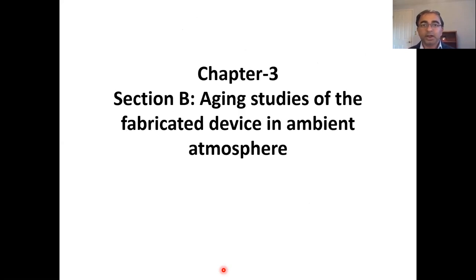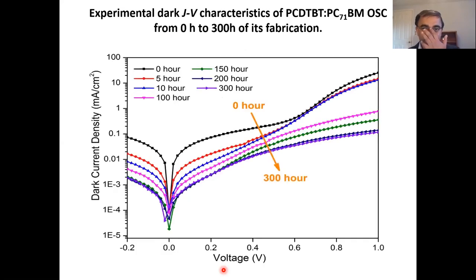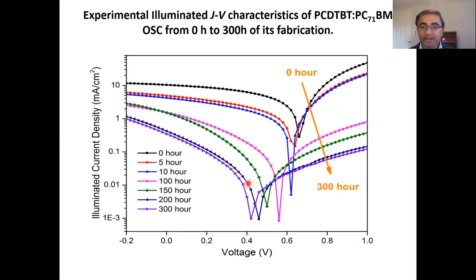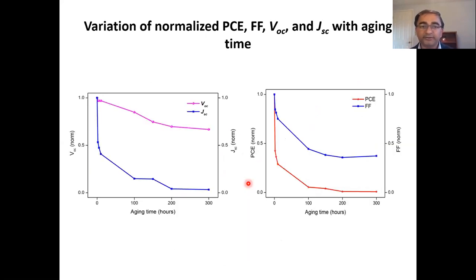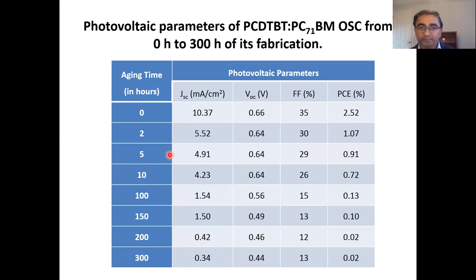So now we have done some aging studies, to see how the degradation of these devices happens. You can see from here, we have measured the current-voltage characteristics from initial to 300 hours. And you can see that there is a degradation of the curves happening with time. We have tried to understand the degradation mechanism behind this. These are all the photovoltaic parameters with aging. You can see from here, they are all degrading with time. Although there is less degradation in VOC, all are degrading with aging time.